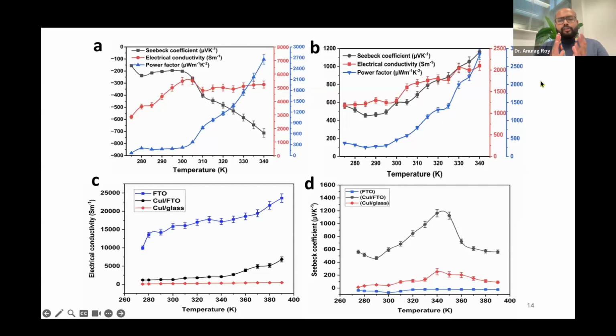You can see that as the temperature increases, the Seebeck decreases. As the temperature increases, the electrical conductivity increases, and the power factor is the overall multiplication of these two parameters, so it generally increases. This one is for the zinc oxide, and this one is for the copper iodide, and they show almost a similar trend. In the case of copper iodide and zinc oxide, only the Seebeck coefficient is different because of its conductivity nature. As the Seebeck is going down, that means it's an N type, and here the Seebeck is going up, that means it's a P type. So only the type of semiconductor is different, the rest of the things are quite expected, and it shows a similar trend, and that also shows a very high power output.